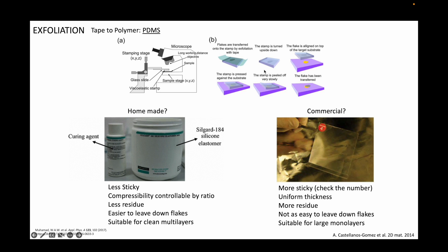In this method, the tape with the 2D material is exfoliated onto a block of PDMS which is attached to a glass slide. The key here is to be as fast as possible when removing the tape. Similar to the inertia experiments with a ball with two strings, more 2D materials are left behind the faster you accelerate the tape away. If you pull away the tape slowly, most of the flakes will remain on the tape. This can also be useful when repossessing the precious 2D crystals from the PDMS back onto the tape.